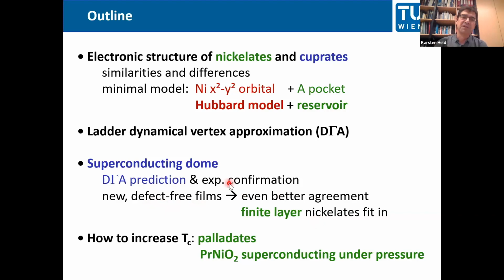Now, of course, this agreement could be by chance, and so it's important to make further predictions and then to see whether it's experimentally confirmed or not. And there are two routes that we looked into more recently. One is to substitute nickelates by palladates. So our prediction is that these palladates should also be superconducting, and the best palladates even a little bit higher than present-day nickelates with a higher TC. We also looked into experiment under pressure.